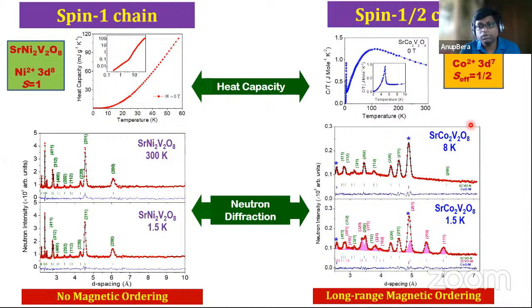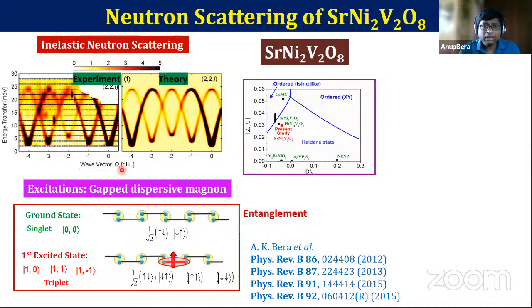On the other hand, for the cobalt compound, if we measure just above the ordering temperature, which is 5 Kelvin, here we measure at 8 Kelvin and 1.5 Kelvin, we do see the appearance of magnetic Bragg peaks, which correspond to the magnetic ordered lattice. So magnetic long range ordering happens for the cobalt compound, while for the nickel compound, there is no magnetic ordering. Now, as proposed by Professor Haldane, the spin 1, which is the nickel-based compound, has a topologically protected ground state and there is a gap excitation.